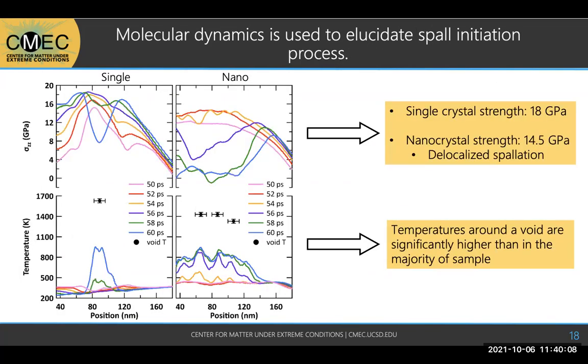We also did molecular dynamics, as I just mentioned, Carlos did. We have here stress profiles and temperature profiles, where we see that the single and the nanocrystalline strength trend follows the experiments. We also notice that in the nanocrystalline simulations the failure is kind of delocalized, so those stress profiles look more like a plateau compared to the single crystal, where you have this massive drop in that blue curve. The temperature was also measured, where the curves correspond to the entire sample and the points correspond to locally around a void. And that local void temperature is much higher, and I'm going to touch on that in a moment.